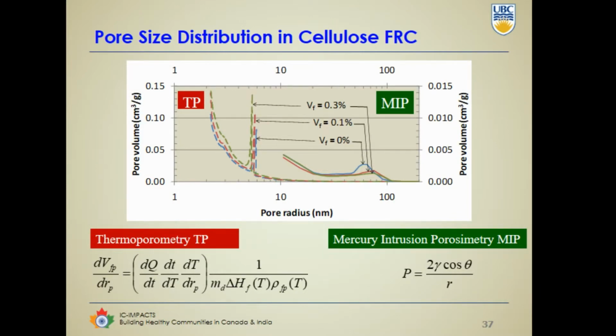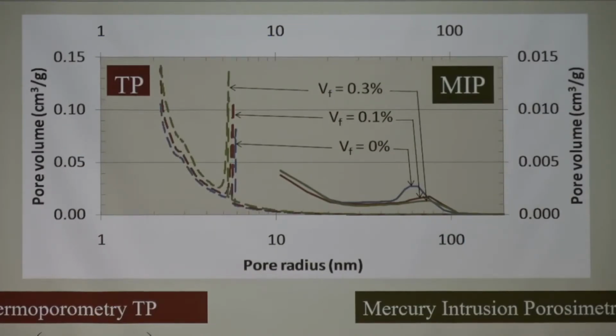What we're doing through fibrillation, here is your 0%, 0.1%, and 0.3% of the cellulose that we are adding. What you will notice is that I'm converting quite a bit of the microporosity in concrete, which permeates. Water can permeate through microporosity, but it does not permeate through nanoporosity. So under 50 nanometers, concrete will not permeate. And what I'm doing through this surface-exalted cellulose is converting microporosity into nanoporosity. And that's very exciting because I'm making concrete far more impermeable.